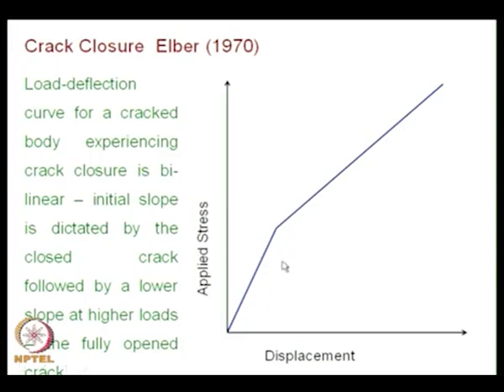Initially it is more stiff; the initial slope is dictated by the closed crack. So, that means the crack behaves as if it is smaller in length. Then you have a slope which is different. At higher loads, because the crack is fully opened, the slope is also different. So, a fatigue cracked specimen experiences a stress displacement behavior that is bilinear, which is a model again; in practice you will have a smooth transition from this to this, and that is also depicted here.